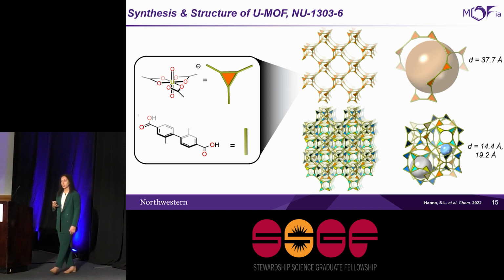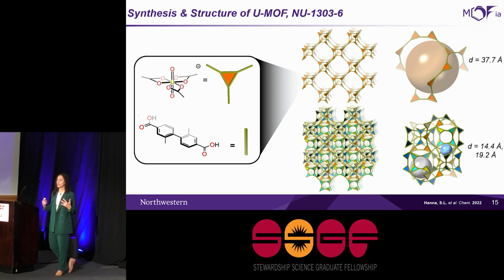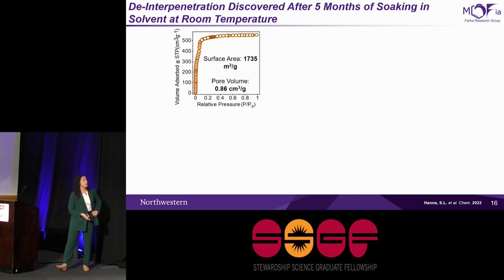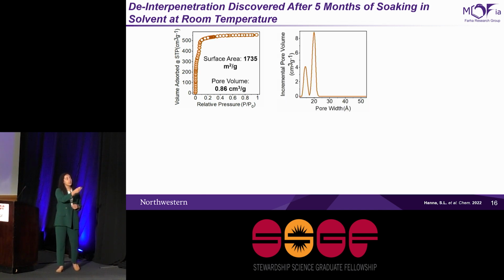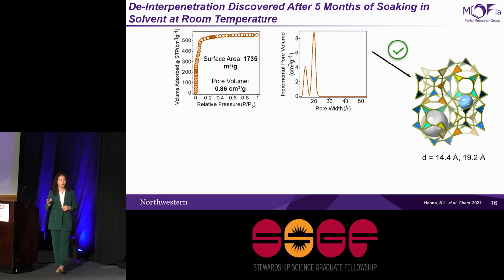So this is a single crystal structure, and after making my single crystal structure, I wanted to make sure that the bulk powder that I made also really matched up with the characteristics of my single crystal. So I ran what's called a nitrogen physisorption isotherm, which is essentially where you take your powder, you dose in a fixed amount of nitrogen gas to your powder, and you monitor the uptake of that gas into your powder on the y-axis. And what that tells you is a lot about the internal pore shape of your MOF. You can extrapolate this data to what's called a pore size distribution, which shows you that I have 15 and 20 angstrom pores. And this matches up really well with what my single crystal structure showed me.